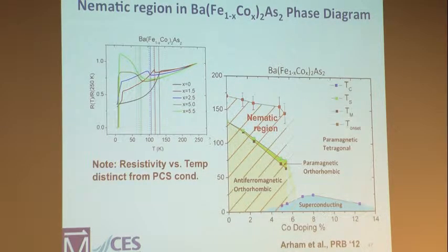Now, this is something that I think really set the stage for us trying to figure out what was going on theoretically. So this is our phase diagram. The points showing the structural phase transition, the magnetic phase transition, and the superconducting phase transition were all taken by Hamoud, and they were taken by looking at resistivity. If you do resistivity versus temperature, you can see those transitions. There are always kinks in the resistivity versus temperature curve. What you don't see is anything that has to do with the nematicity. When you measure these materials using point contact spectroscopy in the right regime, you actually don't see these transitions here, and you only see the onset of the nematic. So we see right now, in your face, resistivity and point contact spectroscopy are different measurements. They're picking up completely different things.